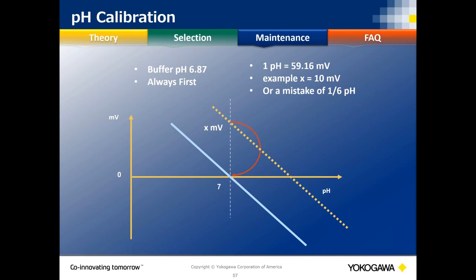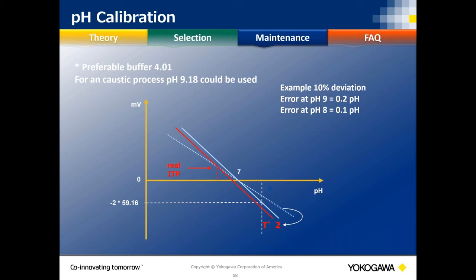So this gives you indication of your reference side of your system, what's going on. Is it being poisoned? Is it being plugged? Is it being depleted? The second point of your pH electrode is when you do your calibration, is compensating for your glass electrode, the aging of it. So now it takes that nonlinear line and linearizes it, and you're accurate over the whole pH range. So that's what we say to do. We say to do a 7 and a 4, and then check with a 10, or do a 3-point cal.